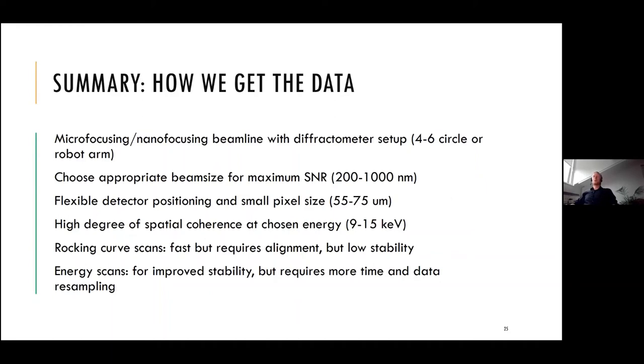Some small summary for this part. Basically, to get nice data, you need to find a microfocusing or nanofocusing beamline with a diffractometer setup. It can be 4 or 6 circle diffractometers. You can choose between beam sizes with full coherence. Normally it's between 200 to 1000 nanometers, but with the advent of new sources, this range can be extended. Use flexible detector positioning and small pixel size to have a nice sampling. And you either do the rocking curve scans, which are fast, but require alignment of the sample into the center of rotation so that you don't lose your sample out of the beam, and have low stability for certain sample environments, or you choose the energy scans for improved stability, where you basically change only the energy of the beam by tuning the undulator and the monochromator. But it requires more time and you need to work on the data resampling a bit more.